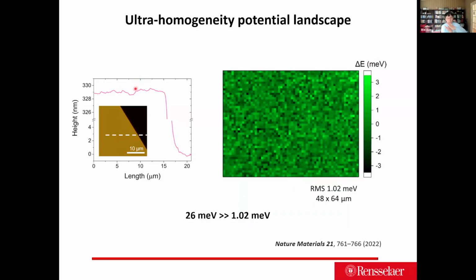If you further quantify that by opening up the cavity and measuring with an atomic force microscope on top, you will see the surface is at sublattice-level flatness. No roughness, really flat. And if you close the cavity without opening it, and just measure the lower polariton mode, you will see the polariton mode has a peak-to-peak variation of plus and minus 3 meV. If you convert it into RMS variation, that means you have 1 milli-electron volt.